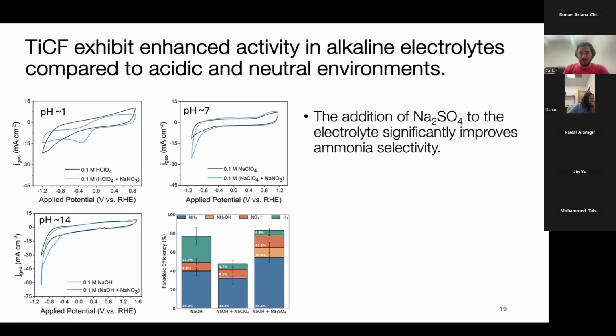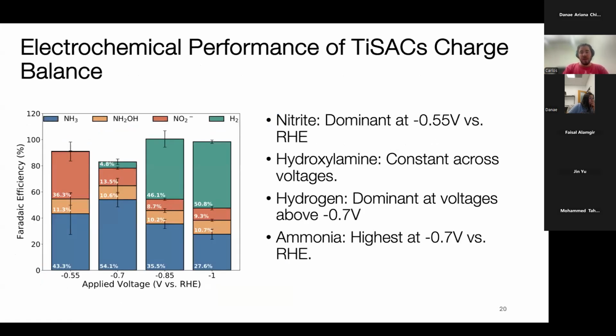But with sulfates, we can close that mass balance to over 90%, and we get pretty good performance for nitrate reduction to ammonia. Now that we have selected our catalyst, we do a bigger survey in which we are trying to survey the different potentials and study the product distribution, and to give us an idea of the mechanisms and how we can improve this reaction further.